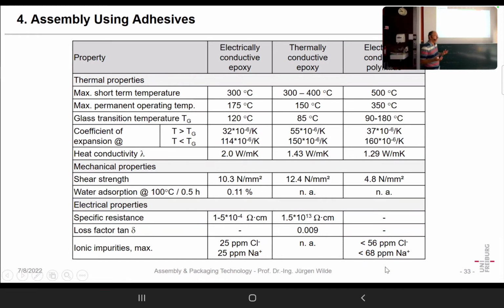On the other hand, if you have bigger parts of material like molding compound or so, the limits are lower for chlorine, but the amount of adhesive in an assembly is so low, let's say it's milligrams or so, so it doesn't matter if it's 10 ppm or 25 ppm, it's just low, but it must be limited in order to avoid problems.